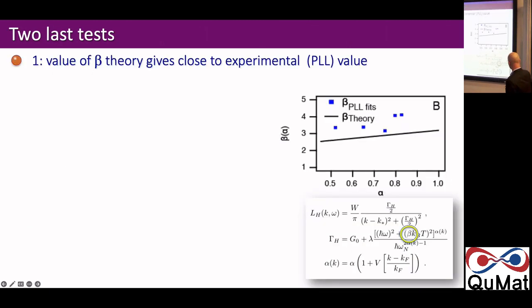One of them is we have in this parallel liquid some coefficient in front of the temperature dependence. This is the balance between temperature and frequency, right? You have frequency squared plus something times temperature squared, all to this power alpha, which is K dependent. So this beta from the parallel liquid fits in experiment is coming out somewhere around about pi and going up slightly. And Henk and Enea are very honest people. They just tell us what comes out of their theory. Now the trend is perfect. It's a little bit on the low side. But there's maybe some space to tweak the gravitational side of the AdS-CFT model to make this fit in the future. But it's the right ballpark for sure.